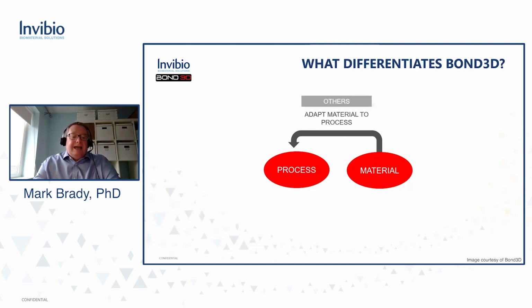Well, for some high-end printers, they've still struggled to print with PEEK, and sometimes the materials had to be modified to meet the machine capabilities. For example, Victrex have introduced a low melt PAEK, which is very similar to PEEK, but it has some of the building blocks in the polymer backbone rearranged. That allows you to open up the processing window a little bit. Bond, however, from the get-go, have focused on developing their machine and process to meet the existing materials, including PEEK-OPTIMA Natural.